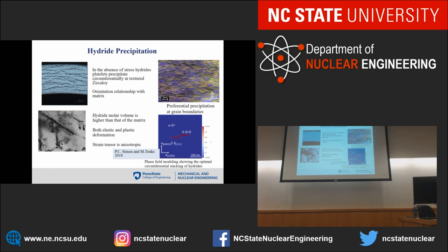People know about crystallography. The hydride is a delta hydride, which is FCC, and the 111 plane of the FCC is parallel to the 001 plane of the matrix. The prevailing texture of Zirc is with the basal planes more or less this way. We also tend to precipitate more at the grain boundaries. You can see the different colors here show the different grains, and the hydrides tend to precipitate along the boundaries. If I have a cold worked material, it's like a stack of pancakes, and the grains are small in that direction and tend to be more horizontal. So I would precipitate preferentially there as well.